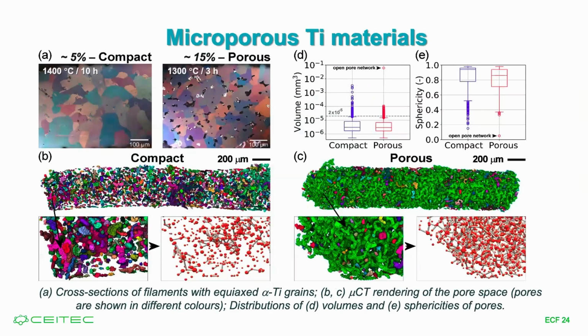So this is an example of two materials we prepared and tested in fatigue. You see this one is sintered at 1400 for 10 hours, and we have very low porosity. We also have larger grains here. And this one, here we have microporosity of 15%. As you can see, we achieve open porosity across the whole printed filament here. We have one large pore and also some small pores which are isolated.